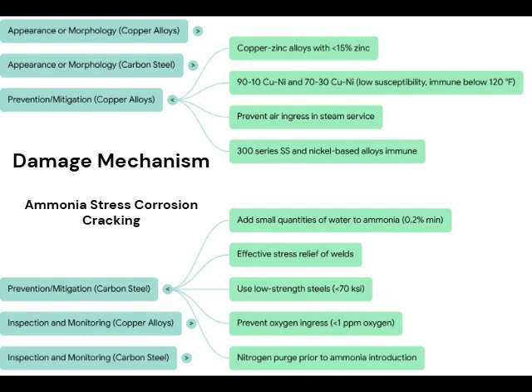You've got liquid ammonia at the bottom and vapor space at the top. Right. Water prefers to stay in the liquid phase. So even if you add 0.2% water overall, the concentration in the vapor space up top can drop way below that critical 0.2% level. Oh, wow. So the top of the tank, the welds up in the vapor space, are still vulnerable. Exactly. Which means you need another layer of control.